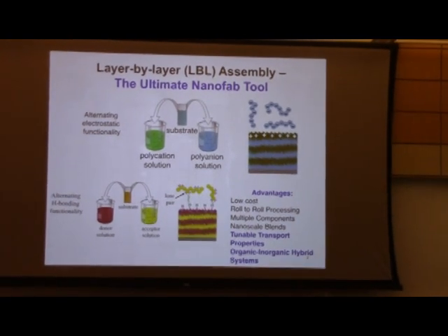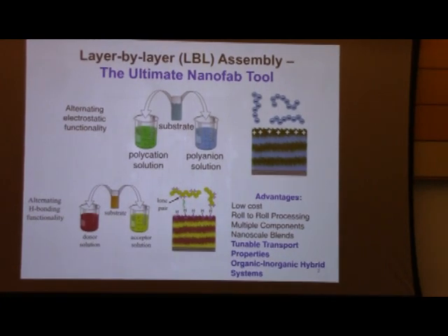So if you had a negatively charged substrate, you immerse it into a dilute water solution that contains a positively charged material, you'll get something that is positively charged in the end. You can then rinse the substrate to remove anything that is not truly absorbed onto the surface and immerse it once again into a water solution that contains something that is oppositely charged. So you can alternate positively and negatively charged species back and forth in series and continue to do this ad infinitum. There's no theoretical limit to how many of these layers you can put down.